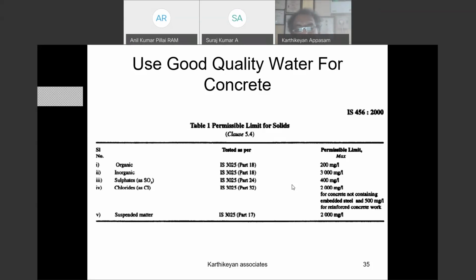The sulfate content shall not be more than 400 ppm. If it is PCC, 2000 ppm. If it is RCC, 500 ppm should be the chloride content.